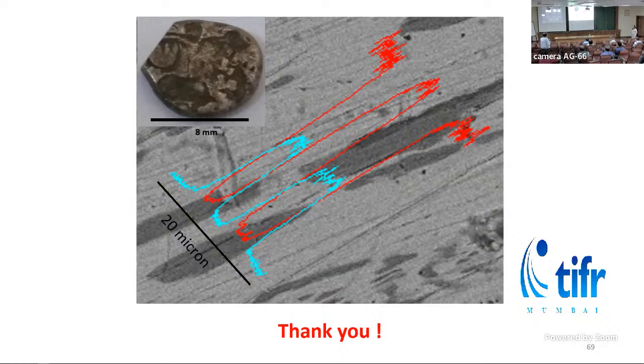I understand these go all the way to a fraction of nanometers, tens or maybe hundreds. So is there a procedure where you do something like a calibration from time to time, that tells you that your instruments are looking at the least counts which are expected? Yes, we have standard samples and we have to calibrate the equipments from time to time. And for the aberration corrected microscope, we have to align the microscope using those standard specifications, and that alignment procedure itself takes quite a long time.